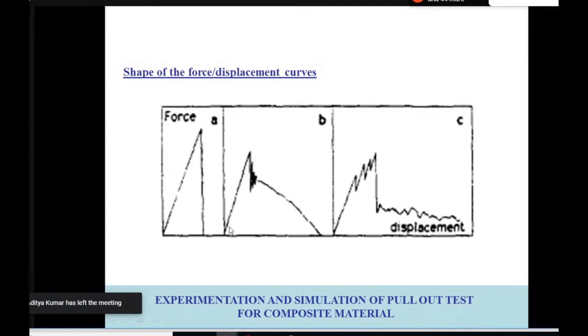The second case: gradually it will give bonding up to a certain limit, and then it will give a resistance and slowly fail. So basically the interface is giving resistance in failure. And the third one, C, is the best case. If you have prepared a staircase kind of thing onto the surface of the fiber, then at every instant it will give you bonding, and it will give resistance by mechanical anchoring. That is why we prepare the surfaces of the fiber. By using a rough surface you can increase the interfacial strength tremendously, maybe from basic bonding to 3, 4 or 5 times, depending upon what kind of mechanical engagement you have been able to generate.